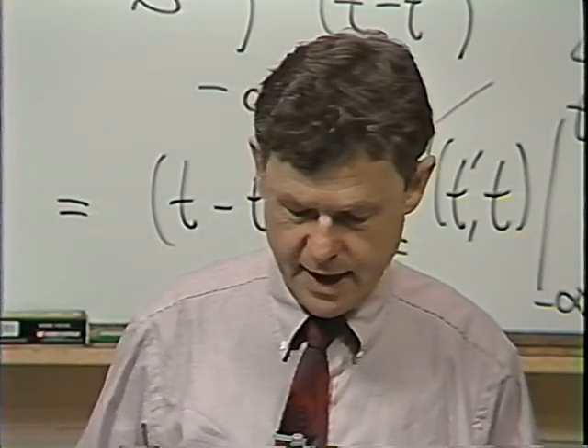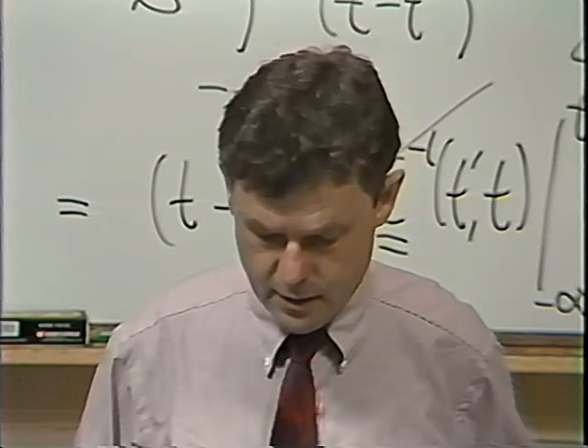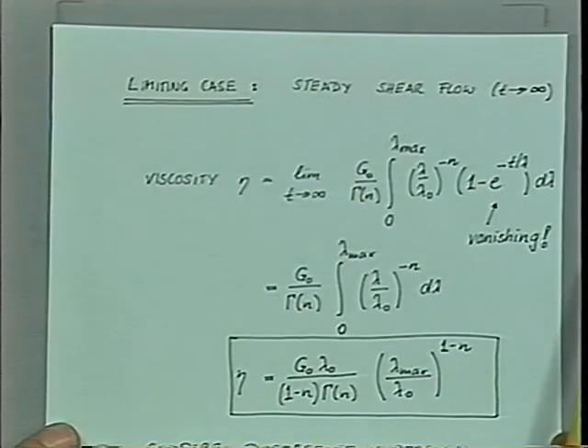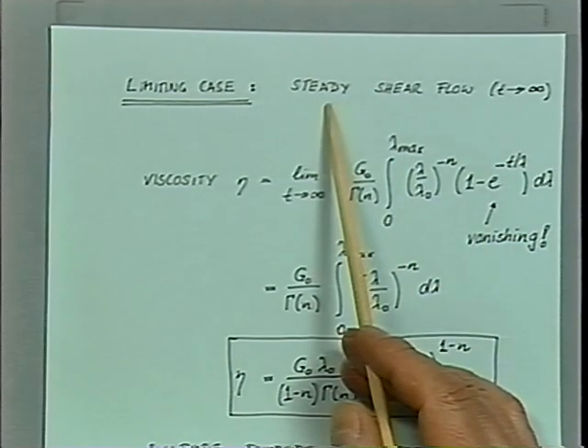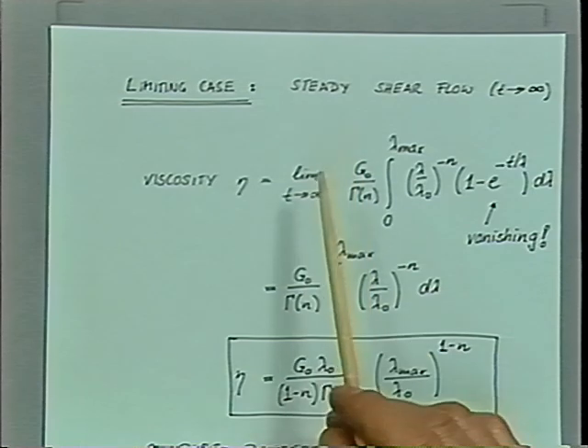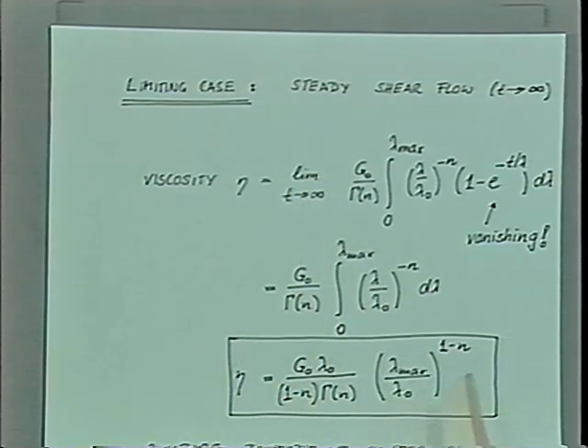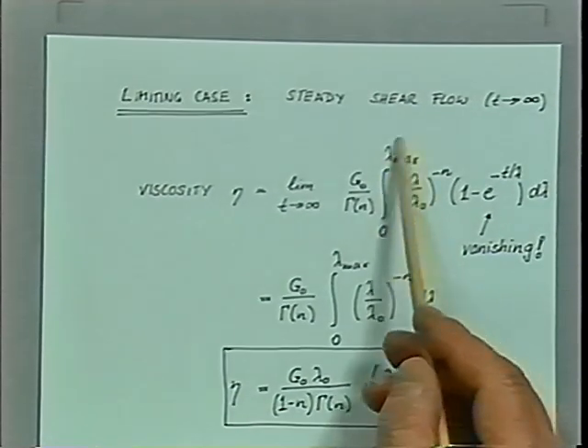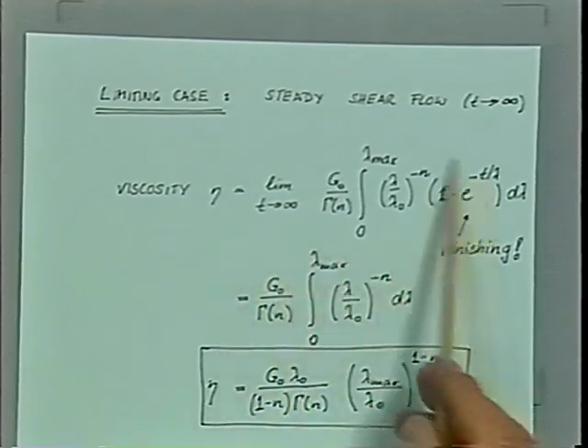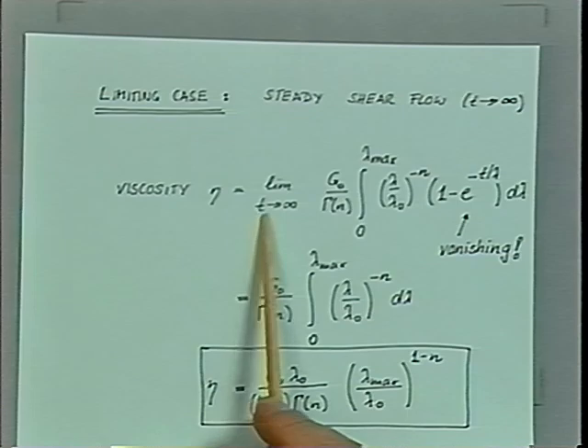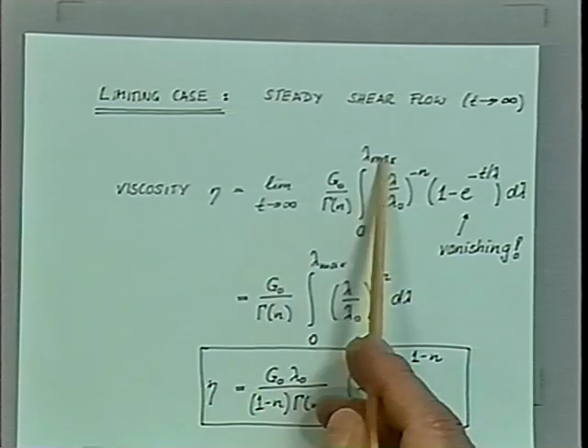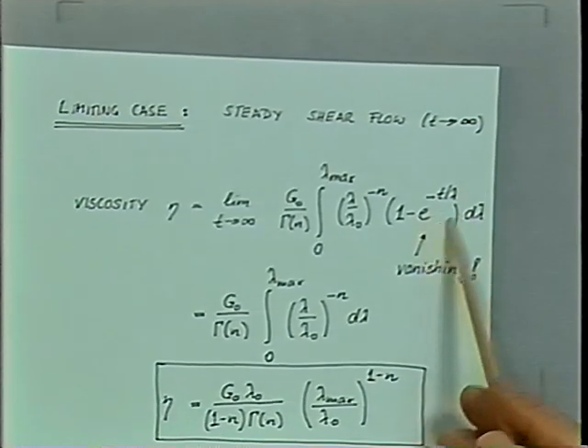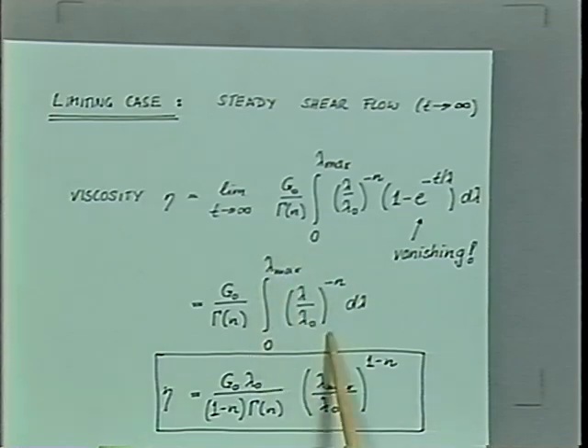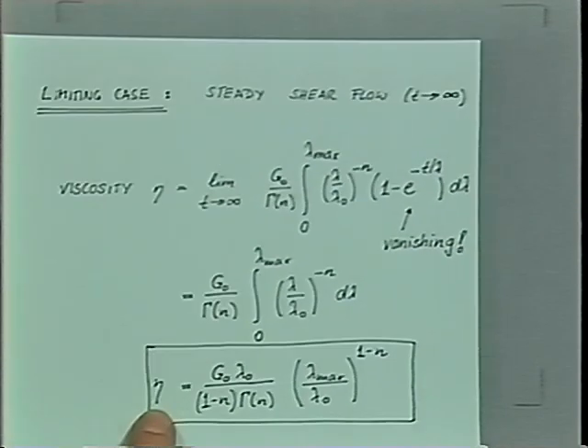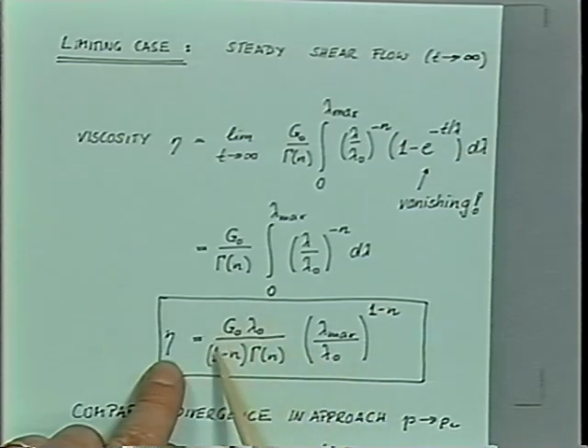Let's look at some limiting cases. Let's look, for instance, at steady shear flow of the nearly critical gel. Lambda max is not infinite, so we don't have any problem of a diverging viscosity. Viscosity is still finite. So lambda max is finite in our calculation. And we just take this expression and say that time should go to infinity, much longer than lambda max. Then the transient part is vanishing, and the solution is just given by this integral, which we can evaluate and can say the viscosity is given by some constant factor times lambda max to the power 1 minus n.